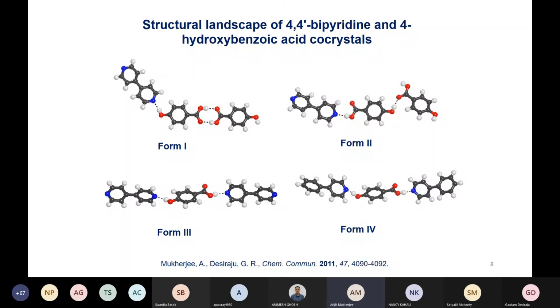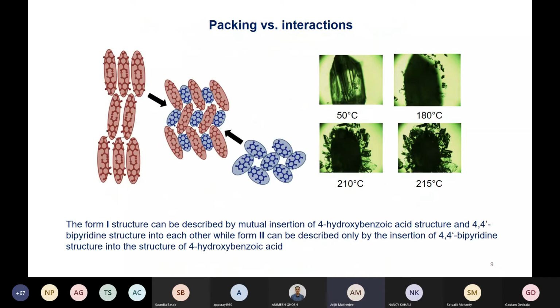And among these 4 forms, form 1 and form 2 are called synthon polymorphs because their compositions in the asymmetric unit are the same. So you can see here, in the first case it forms an acid-acid dimer and then a pyridine OH synthon. And in the second case, it forms the other way around. It forms the acid pyridine synthon, whereas the OH group interacts with the COOH group of the other molecule. So we questioned ourselves why does it happen?